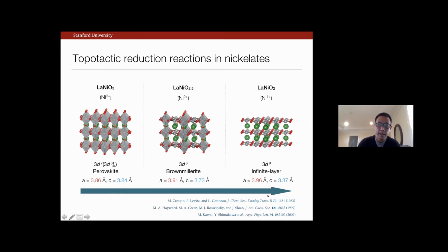Okay. So this sequence of reactions was first reported in 1983 using hydrogen gas for reducing powders. There are many experiments in this field, but to take these three highlights, the next critical step, certainly the one we're utilizing, is the work that found that the stability and reproducibility of this reduction reaction could be greatly enhanced by using metal hydrides.